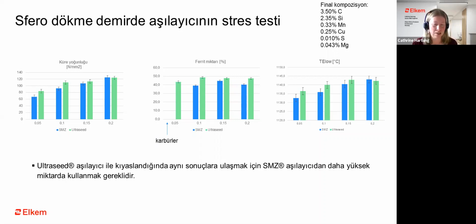But Ultraseed cerium, however, was specifically developed for ductile iron and specifically for ductile iron with poor nucleation potential. And it is designed to provide good performance with minimum addition and to allow the foundry to operate with high carbon equivalent and silicon in the furnace, so that you can have just a small inoculant addition and have packed all your silicon units in the furnace where they are cheaper.